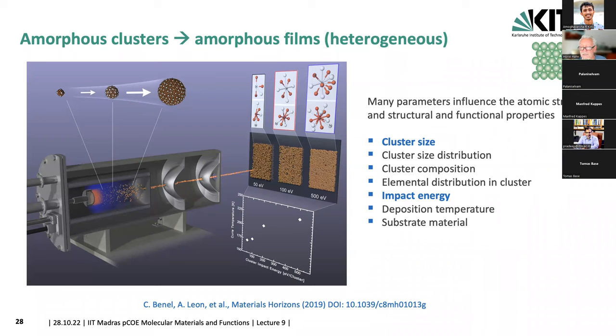And then we can easily look at the magnetic properties, and there is a Curie temperature, so the transition from ferromagnetic order to paramagnetic behavior. And this is given for this iron scandium system at that composition for a Curie temperature which is around 225. As you can see here in the graph, which I show in a minute again, the temperature at 500 eV is actually exactly where we would have it for a rapidly quenched material. So we smash them hard enough on the surface, it's rapid quenching, and we get the structure of rapid quenching. But then we see that as we decrease the impact energy, we have lower and lower Curie temperature. So there is less of a magnetic ordering in there, or less strong magnetic ordering. And you see the Curie temperature can be up to 50 to 60 degrees Kelvin lower.